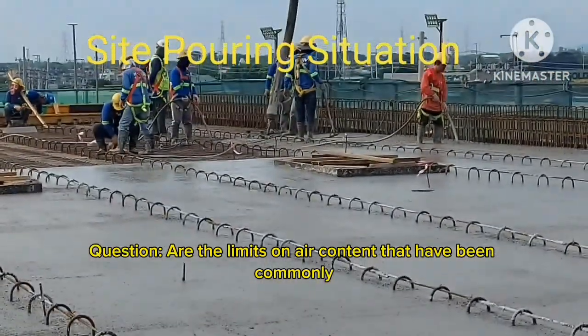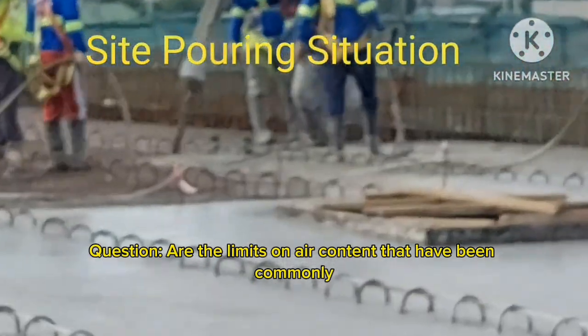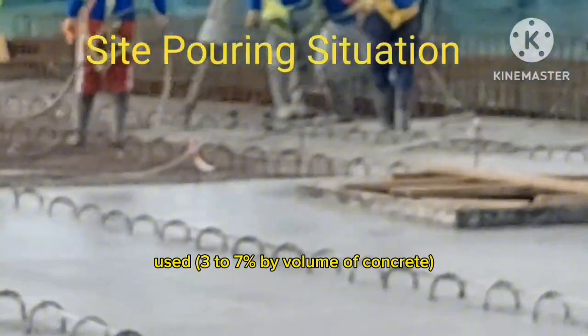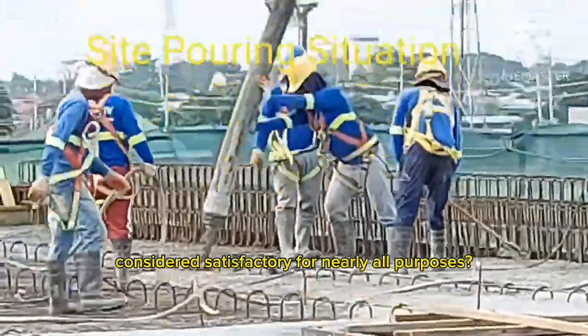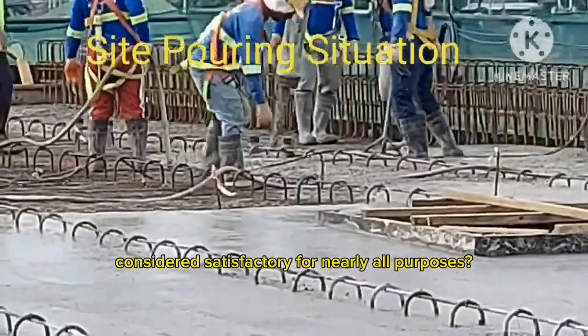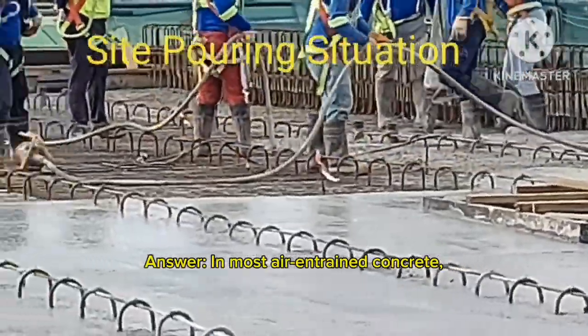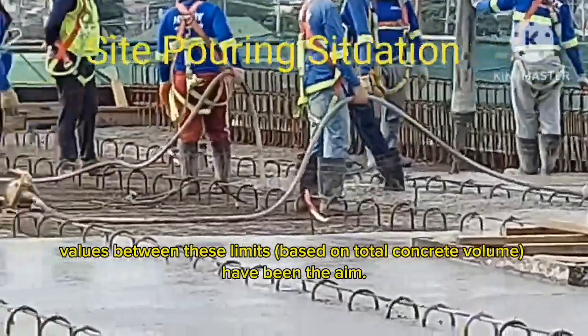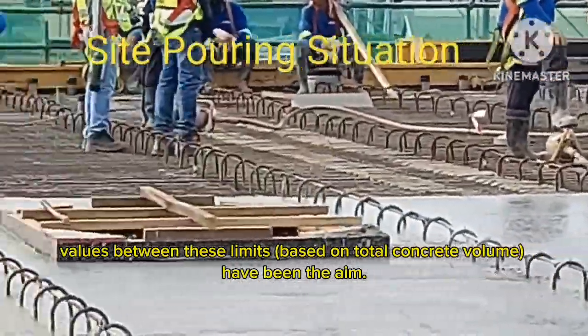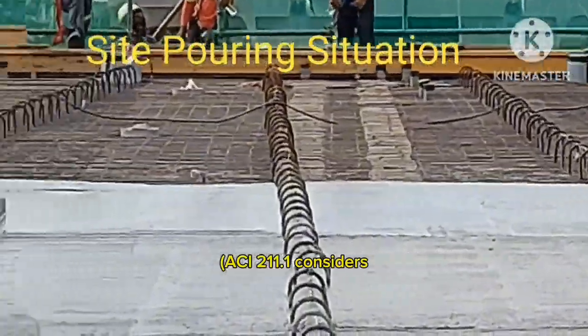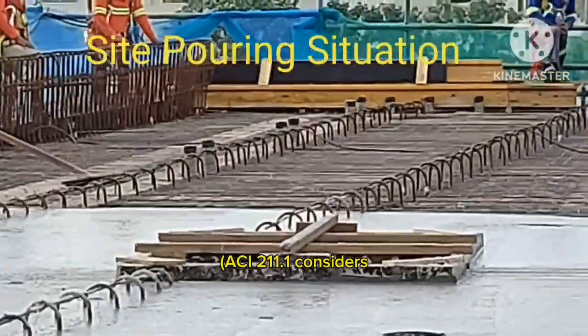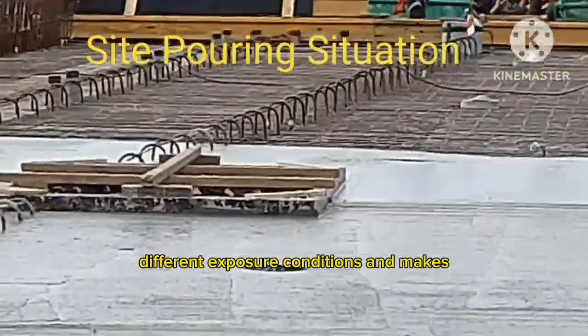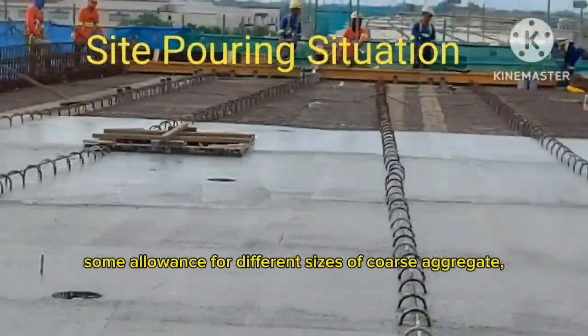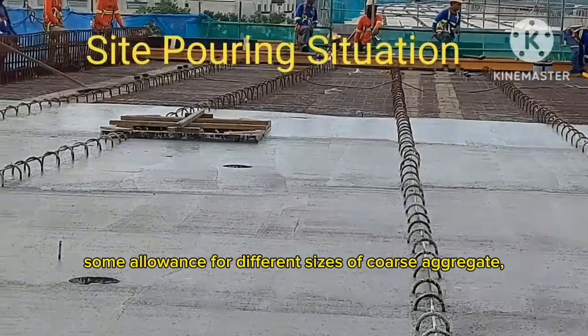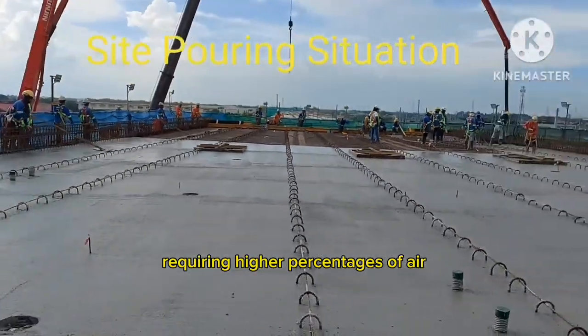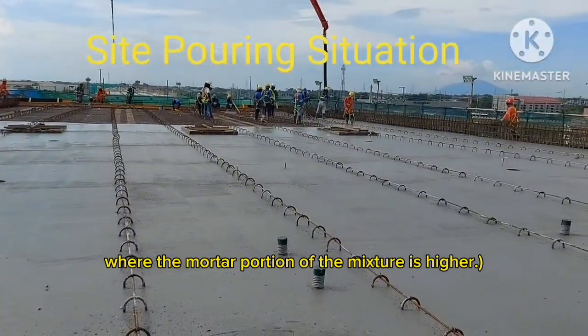Question: Are the limits on air content that have been commonly used, 3 to 7% by volume of concrete, considered satisfactory for nearly all purposes? Answer: In most air-entrained concrete, values between these limits based on total concrete volume have been the aim. ACI 211.1 considers different exposure conditions and makes some allowance for different sizes of coarse aggregate, requiring higher percentages of air where the mortar portion of the mixture is higher.